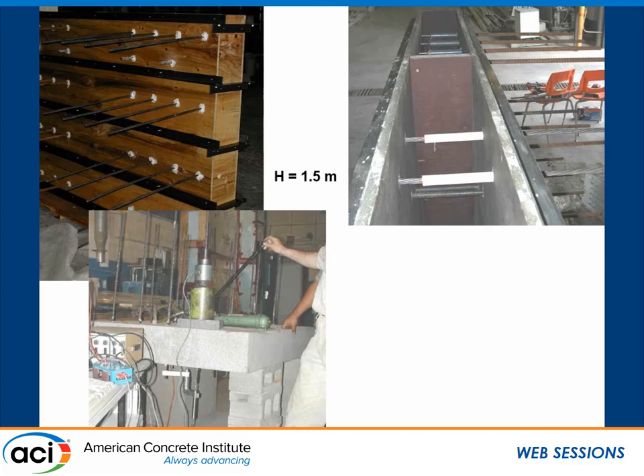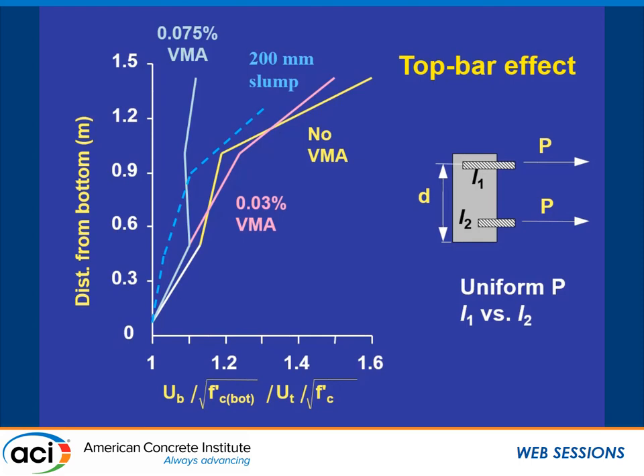So what you have here on the vertical axis is the distance from the bottom. So there are four rebars or four strands at four different depths. And on the horizontal axis, you have the top bar effect. Top bar effect, you can think about it as the ratio of the embedment lengths at the top, L1, divided by the embedment lengths at the bottom, L2, to develop the same pull-out load, not stress, load. So in order to have the same kips of pull-out load, how much more embedment?